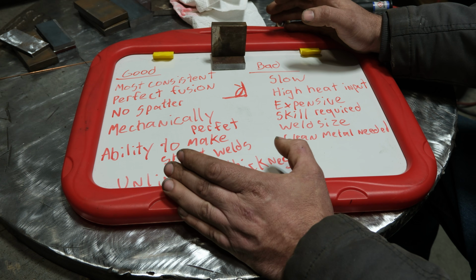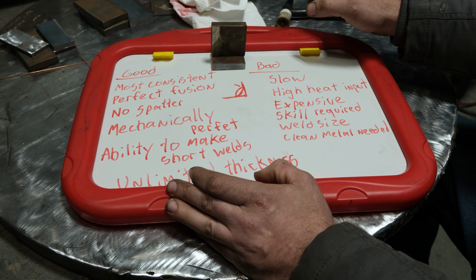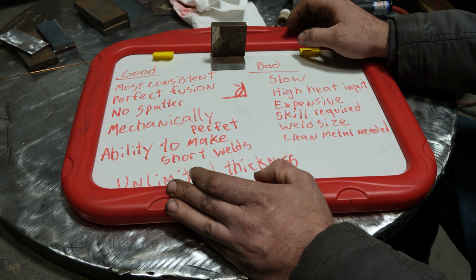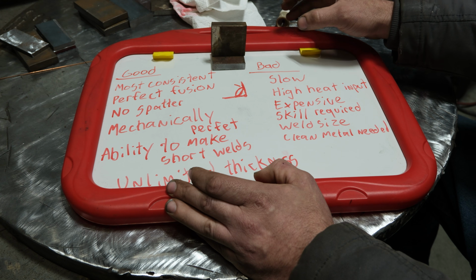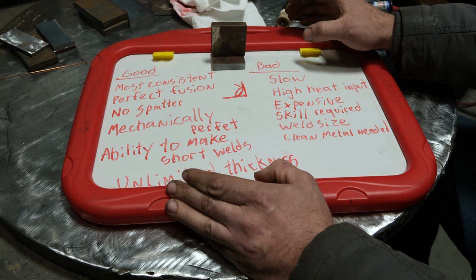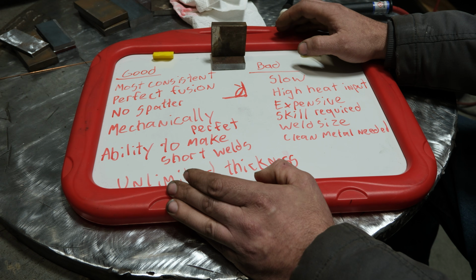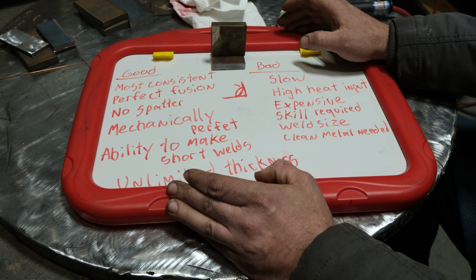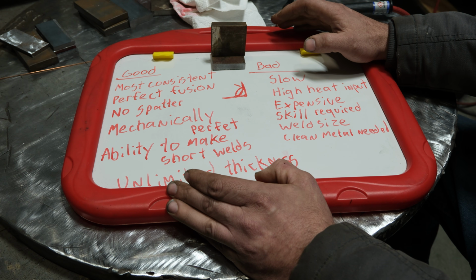So the gist of what's going on here is TIG is really good at making small parts, welding on small items that are very thick steel, having absolutely perfect, the most consistent fusion, and it can make arguably the strongest welds out of all of the processes because they're defect-free and they don't have lack of fusion and all those issues that can come with the other processes, okay?